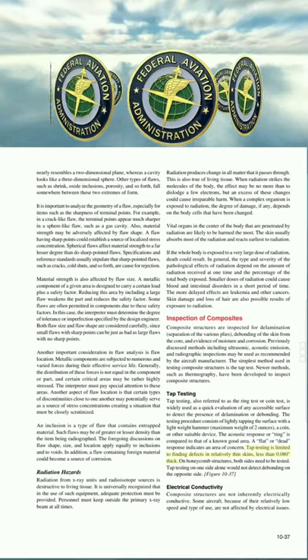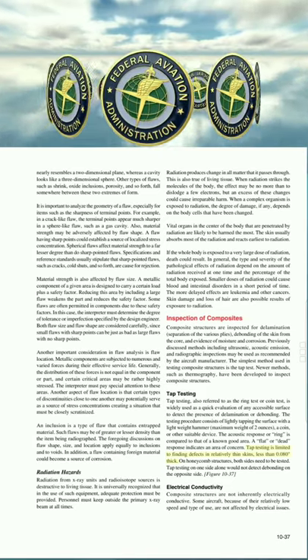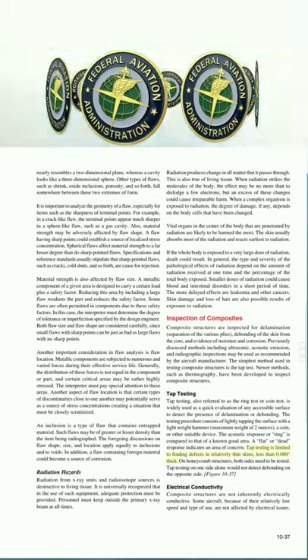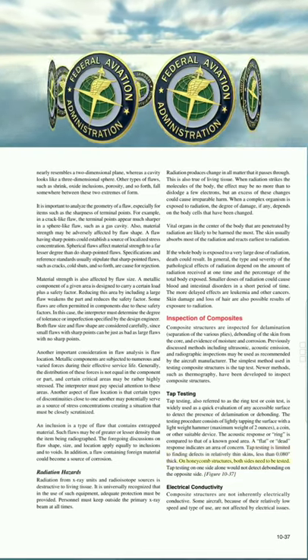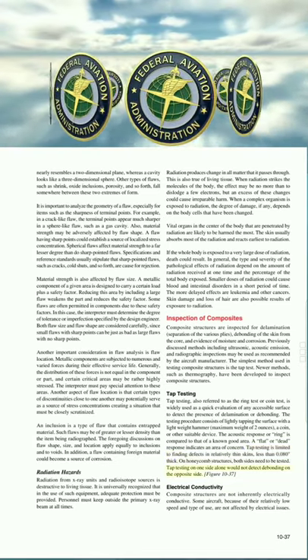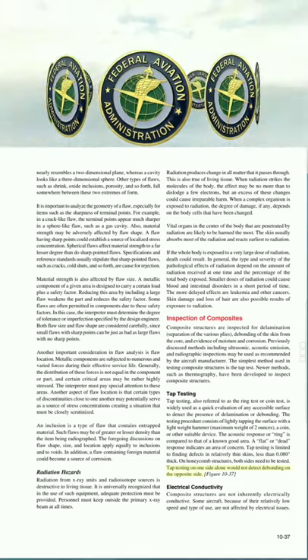Tap testing is limited to finding defects in relatively thin skins, less than 0.080 thick. On honeycomb structures, both sides need to be tested. Tap testing on one side alone would not detect debonding on the opposite side.